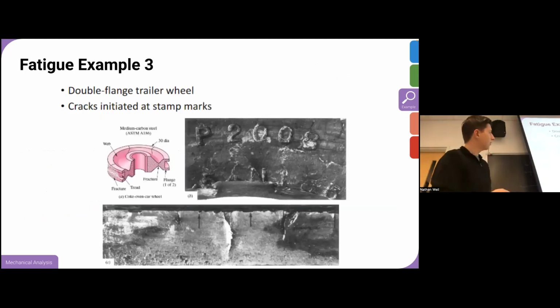Okay, another thing. I've never seen a picture of the actual wheel, but this is from Shigley's also. In this case, this wheel cracked at the stamping marks because it doesn't take a ton for cracks to form around sharp corners. Even though these corners are really tiny, it can still be enough to propagate a fracture. So it's pretty interesting, surface finish can play a role. A cast part versus a ground or polished part can have different fatigue lives based on the surface finish. An interesting thing to keep in mind.